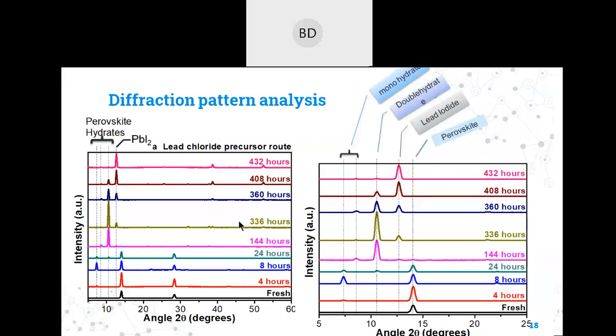Even after 4 hours for lead chloride route, if you can see it here in the magnified image, there is a little signature for some other peak, and it starts increasing with the aging time, and suddenly after some time it converts into some other 2-3 peaks, which shows the formation of the perovskite hydration. These peaks correspond to the formation of the perovskite hydration, where the peak which is around 7 degree or 8 degree is the monohydrate phase of the perovskite, and the peak here which is around 10 degree is the dihydrate phase of the perovskite.